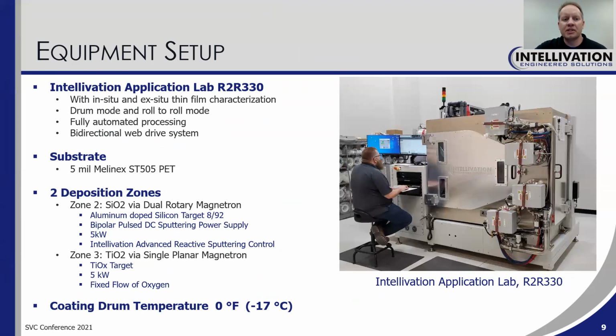The equipment setup we're going to use is an Intelivation Application Lab R2R 330. So this is a tool permanently installed here at our factory, where we do this type of work and do demonstrations. It's equipped with in situ and ex situ thin film characterization. We also have the drum mode and roll-to-roll mode, fully automated processing, and bidirectional web handling system. The substrate we used in this case is a 5 mil PET, and we're using only 2 of the deposition zones in the machine. In one zone, we're depositing SiO2 via dual rotary magnetron sputtering in a reactive process. And then in another zone, we're depositing TiO2 via TiOx target.